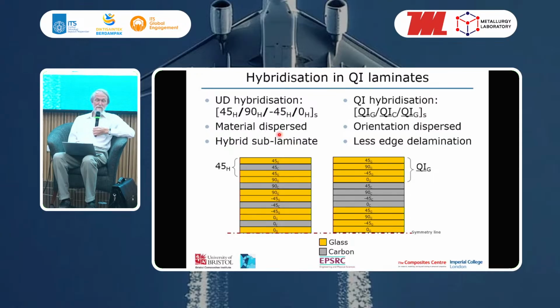And that one we call material dispersed, where we have hybrid sublaminates that are then stacked at different angles to each other. Or the other way we can do it is to take a glass quasi-isotropic, a carbon quasi-isotropic, and a glass quasi-isotropic, and then sandwich those in this way here. So that's an alternative way of doing it; this one we refer to as being orientation dispersed, and we've looked at both of these. They both produce a pseudoductile response, but this one tends to produce fewer issues with edge delamination. One of the interesting things with composites is that they can be susceptible to delamination from free edges, and by reducing the Poisson ratio mismatch, in this case here, we reduce the tendency to get edge delamination.